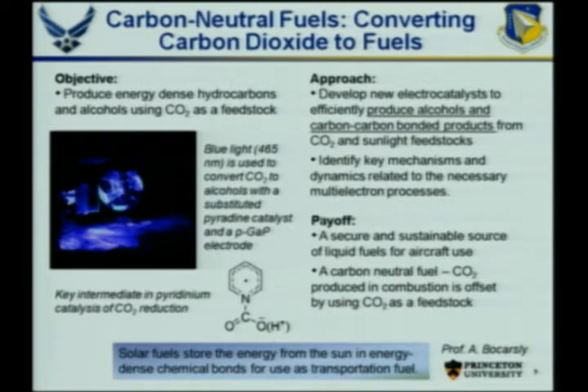And it turns out that they do this with something called pyridine, which is a common organic chemical. It's like a benzene ring with one of the carbons replaced by a nitrogen. And this would be a hydrogen down here in pyridine. But it turns out that if you react CO2 with pyridine and different electrodes, in this case a gallium phosphide electrode, you can start creating these larger carbon chains. You can create alcohols and larger alcohols in this chemistry, depending on the combination of the electrode and the catalyst that you use.